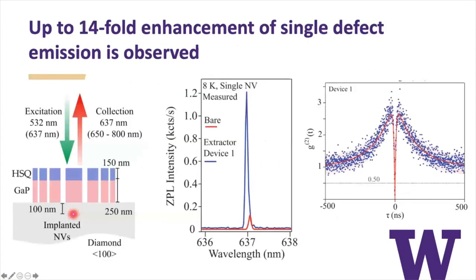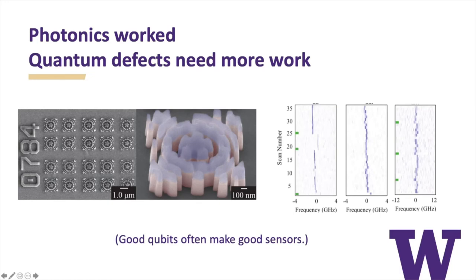And indeed, you can see if you have a defect that's not under one of these structures, this is about the amount of light that you get out at the zero phonon line. And if you have one that's pretty well coupled, then we can get many more photons out. In addition, we can always confirm that we're looking at a single photon emitter by doing this autocorrelation measurement. In this case, we found even this very mild fabrication where we don't etch the diamond. These are very sensitive sensors. They know the qubit underneath, something has happened to its environment slightly. We can see that its line width has broadened somewhat. You can see the scale here is about 3 times larger. And we're working now on trying to figure out what has happened, what happens during fabrication that does this.